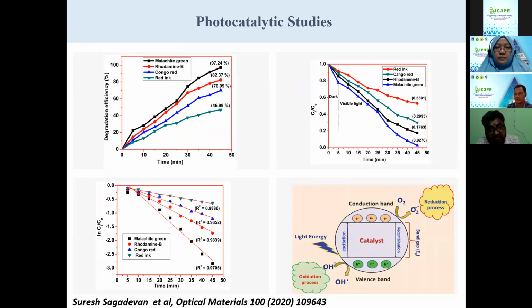The red ink solution is confirmed at 46.99%. So it is observed that the photodegradation of all the tested dyes and solutions is extremely slow in the absence of catalyst under visible light illumination. So we observed a significant change in the degradation of organic dyes like MG, RhB, and Congo red dyes and red ink solution, indicating the role of the photocatalyst in the dye degradation process. This is confirmed in the figure, the degradation with irradiation time.